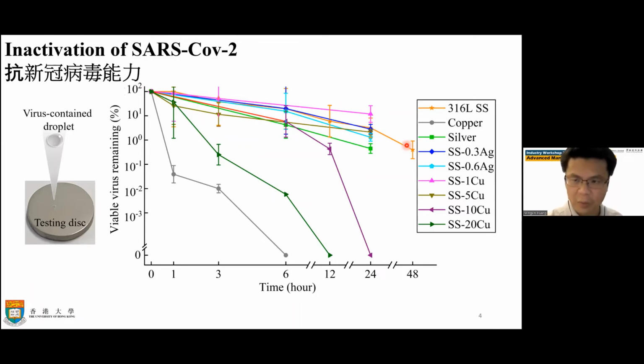Because copper and silver are known for antibacterial properties, and antibacterial is very different from antivirus, we also tried pure copper and pure silver. At the very beginning we thought pure silver might also be used as an antivirus because it is good for antibacterial, but our results show that silver is not much better than stainless steel. In other words, silver itself is not working for antivirus properties.